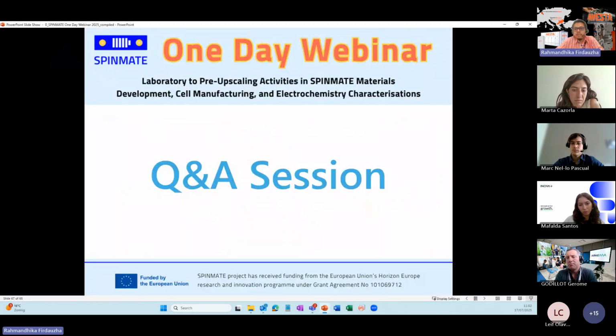Okay. So during making there will be no pressure, but for the test, of course, we need the pressure, especially for the solid polymer electrolyte, at least in this configuration. Then there are other configurations, and yes, we hot press in a different process, but in the SPINMATE context, we don't. If you remember, in a commercial battery as well, when we put the pouch cell inside the module, they will try to limit it with pressure as well, right? Okay, yes. Thank you, Marta.